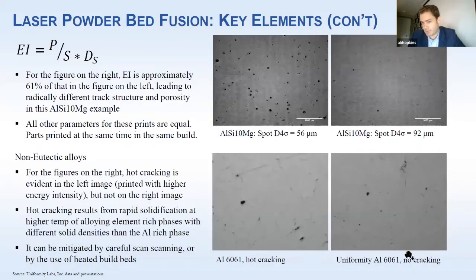6061 is not available commercially for laser powder bed fusion, by the way. Uniformity puts out a binder jetting version, actually, that sinters to 99.8% density, full density, if you will, 99.7%, and that has material properties that are comparable to ingot. And it's an interesting material, and it's interesting why that happens. We'll get into the physics of sintering in a little bit. We just won't go in as deep.